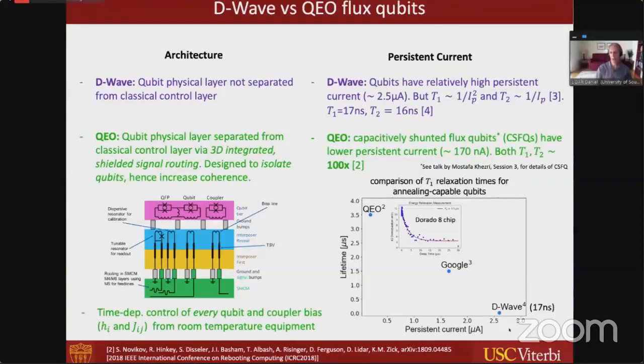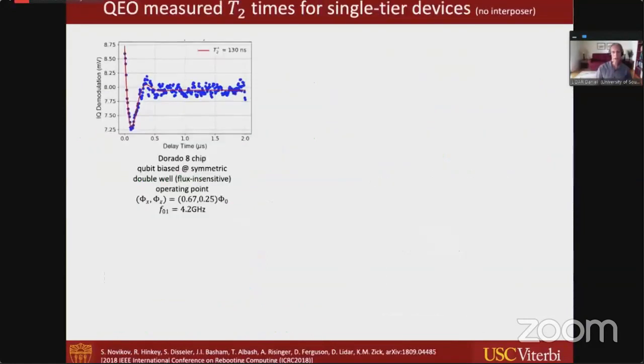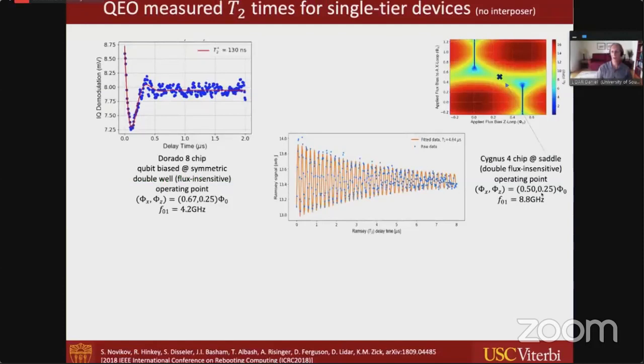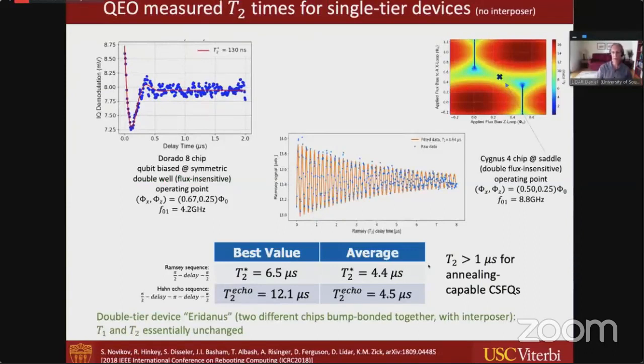The T1 as a function of persistent current. What you're seeing here are the results reported by DWave, by Google, and by QEO. And here's the actual measurement of one of our 4th generation chips with a T1 of 3.5 microseconds. We also measure T2, of course. And so here's an example of the same 4th generation chip with a T2 measured at the symmetric double well or flux insensitive operating point, 130 nanoseconds T2 star. And if you measure at the so-called saddle point, the double flux insensitive operating point, we found a T2 of about 4.5 microseconds. So the summary is the CSFQs so far, at least in the so-called single tier devices without the interposer, have consistently demonstrated a T2 at the saddle point well over 1 microsecond.